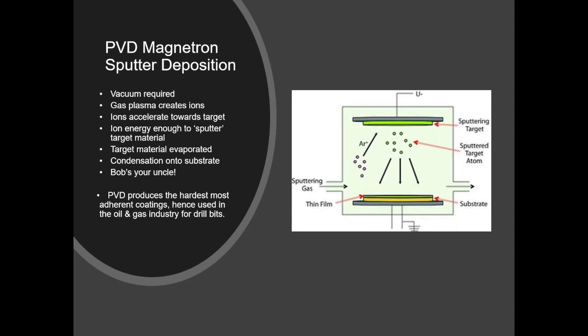We then excite the ions in that plasma and accelerate them towards the sputtering target. You can see there, that's the material that we want to deposit. The argon hits that sputter target. The sputtering target emits atoms and ions, and these are directed towards the substrate or your product, and we coat that with a thin film.